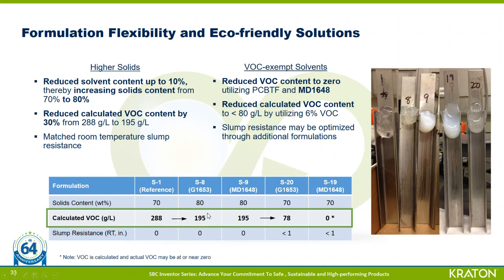We left the types and ratios of all the other ingredients the same in this case, and we were able to effectively drop the VOC below 200 grams per liter to 195. So that's a 30% decrease in VOC by simply removing some of the solvents. We then performed the same action with MD1648 and yielded similar results due to the benefits that these lower viscosity grades provided.